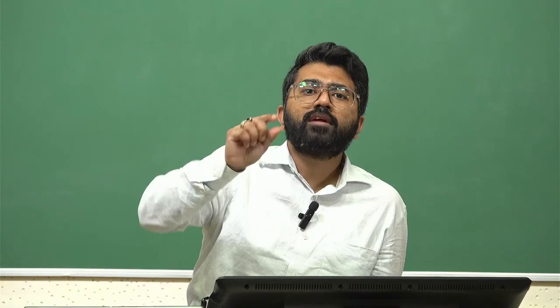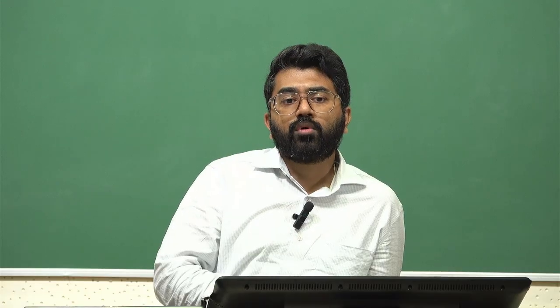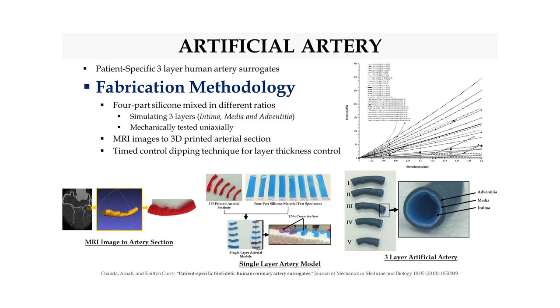So, one of my jobs for a few months was to do this time control dipping all through the day to figure out after what time you should dip to get the amount of thickness which I desire. That thickness is very clear from the literature, right? After doing all this exercise, I could come up with the most perfect artery model. This is what you are seeing on the very right bottom. This is an arterial model with a clear intima, media and adventitia, exactly the same layer thickness as it should be in a real coronary artery, and the mechanical properties are also very similar.